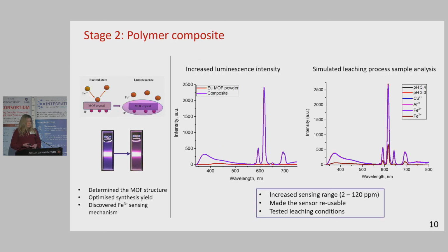Then, when we encapsulated this powdered material in a polymer composite, we saw that these 2 materials have a synergetic relationship. The polymer increased the luminescence intensity, which you can see in the first graph. In red, we have the intensity of the light that is emitted by the MOF powder, versus in purple, where we have this composite material luminescence intensity. This is important because the intensity of the light is what we are using to measure how much iron we have in our solution. That also increased the sensing range of the sensor.